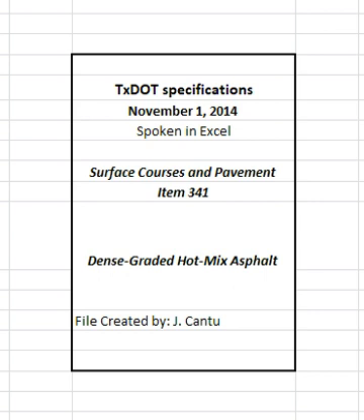4.9.2.4.4 Hamburg wheel test. The engineer may perform a Hamburg wheel test at any time during production, including when the boil test indicates a change in quality from the materials submitted for JMF1. In addition to testing production samples, the engineer may obtain cores and perform Hamburg wheel tests on any areas of the roadway where rutting is observed. Suspend production until further Hamburg wheel tests meet the specified values when the production or core samples fail the Hamburg wheel test criteria in Table 10.